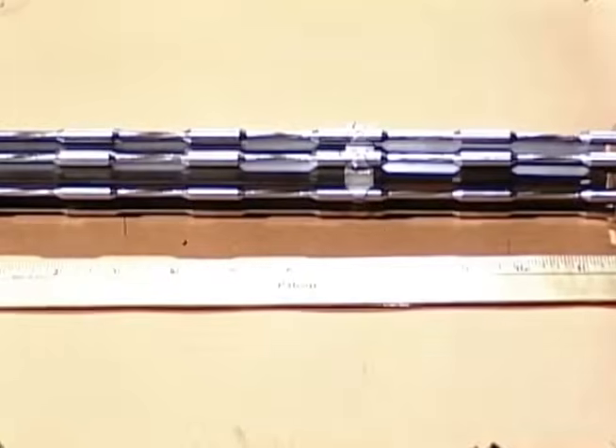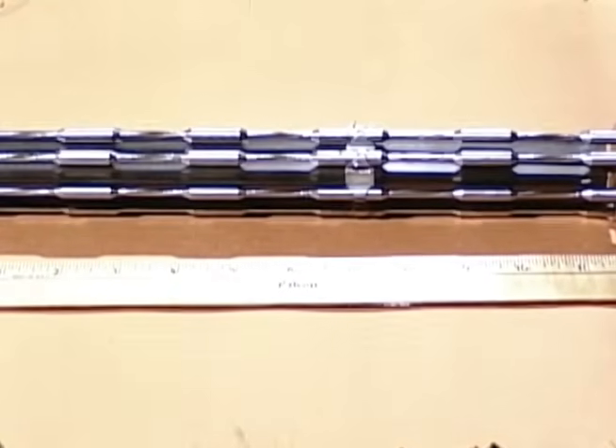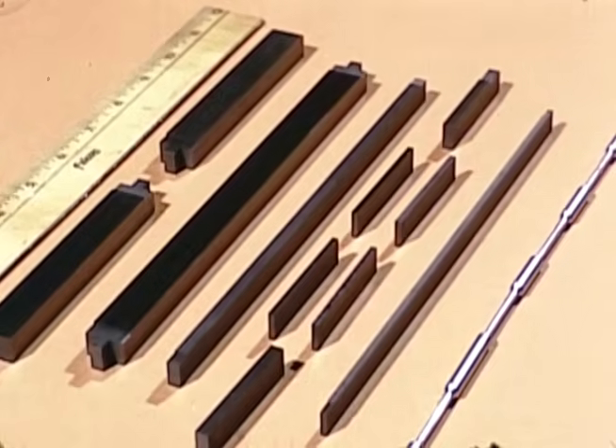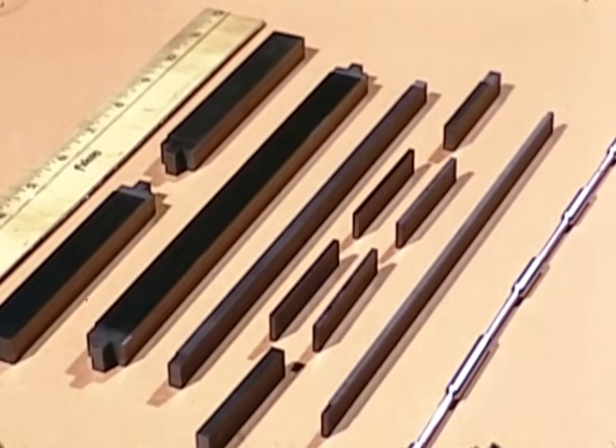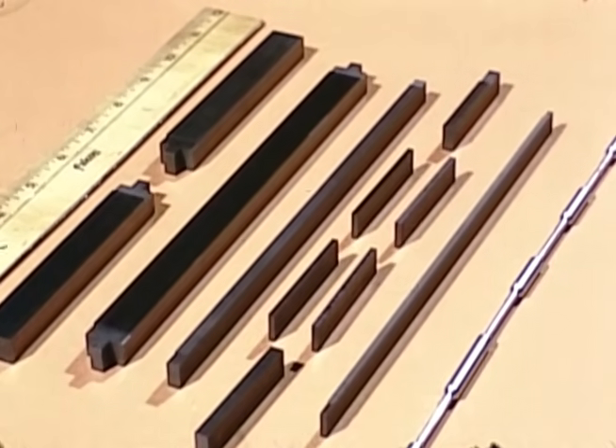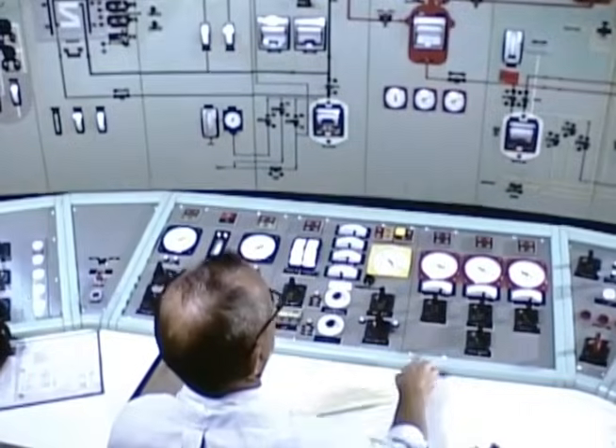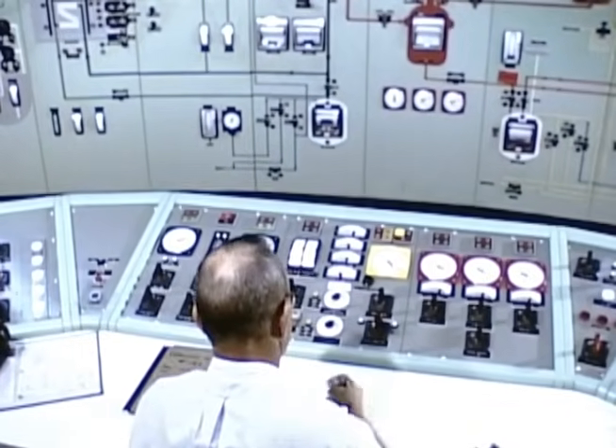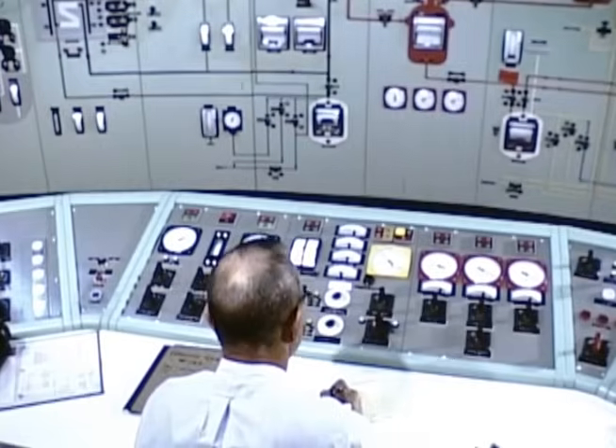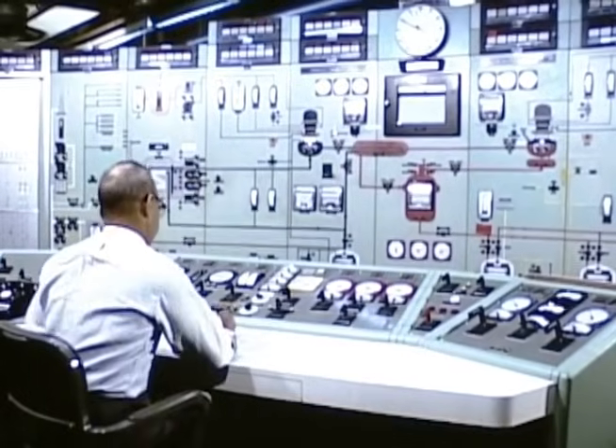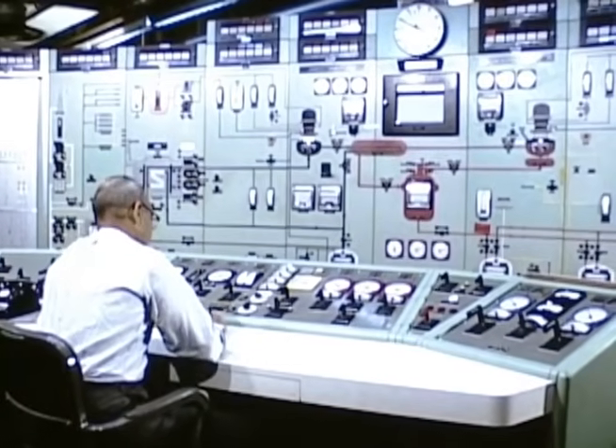Graphite and Hastelloy N specimens similar to these have been removed from the fissioning fuel stream in the reactor core. Examination of specimens in hot cells indicated no deleterious corrosion or structural change after salt had been circulated in the fuel system for more than 6,000 hours. In that time, the fuel proved to be stable to radiation and heat. The reactor, with its 1200-degree core outlet temperature, is one of the highest temperature reactors operating today.